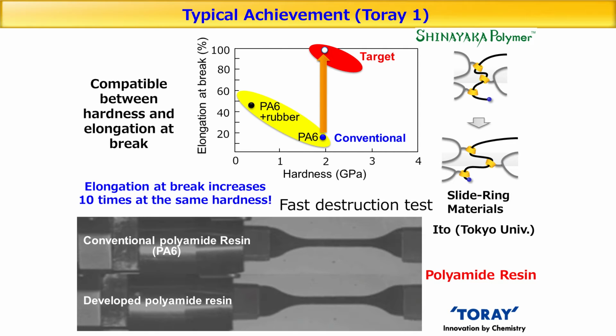However, this made it very soft and flexible. Balancing strength and this tensile elongation and maintaining hardness is a trade-off. If you prioritize one, the other suffers. But in collaboration with Toray, we modified the nylon into a necklace-like structure. Because of this, we were able to increase the elongation tenfold while maintaining the same strength, and it didn't break.